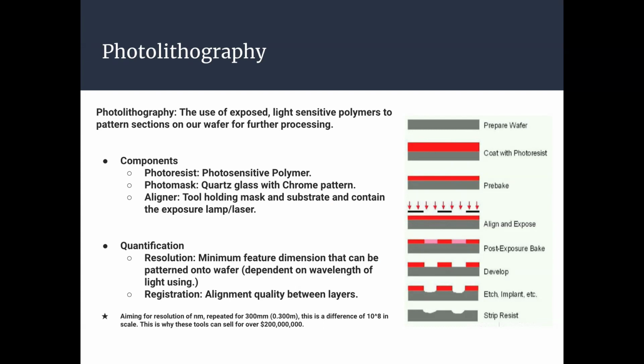Just so you get a sense of the scope we're working with, the smallest nodes now are about 3 to 5 nanometers, and this is repeated across 300 millimeters. This is a difference in scale of about 10 to the 8. That shows you the difficulty we're working with, and that's why these tools can go for well over $200 million.